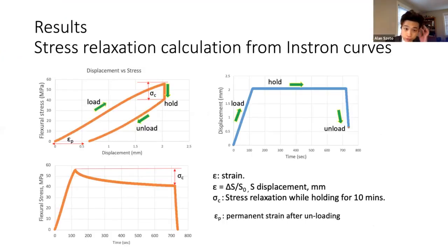These graphs can give a better picture of what is actually happening during the experiment. So if you look at the blue line, you have the Instron machine putting load onto the specimen, and it holds for 10 minutes and then unloads. And during that time, you see the relaxation here, the stress relaxation while holding for 10 minutes. And then you can also see the permanent strain after unloading in this graph.